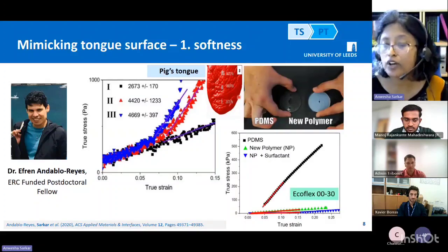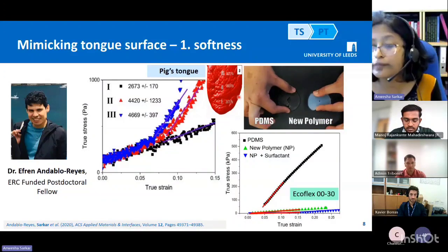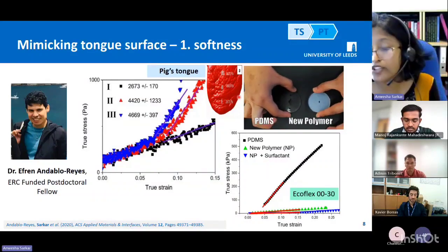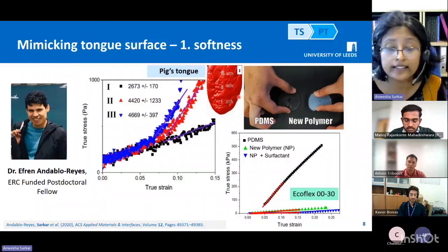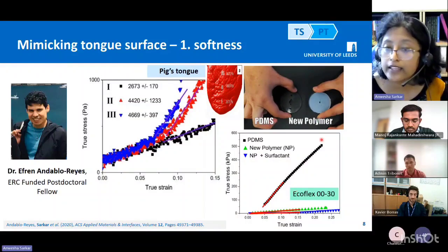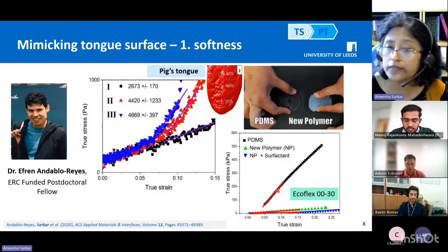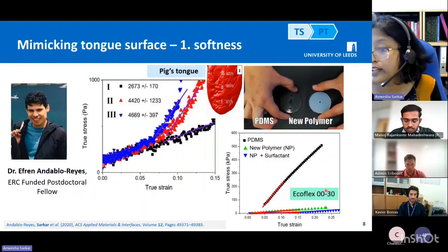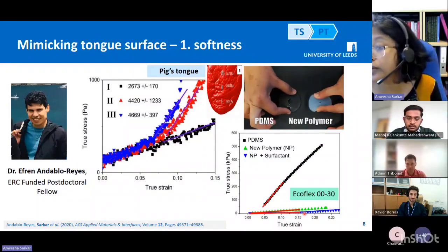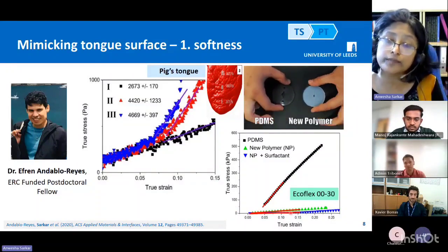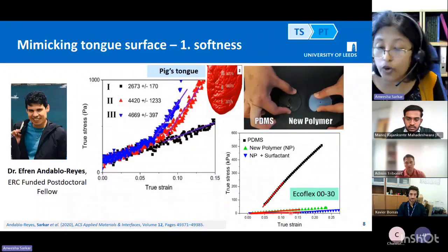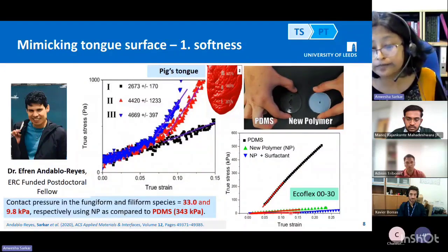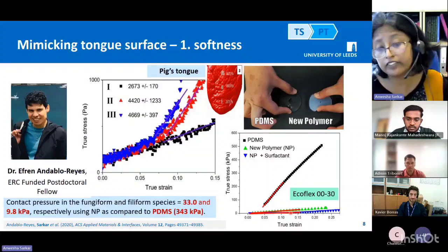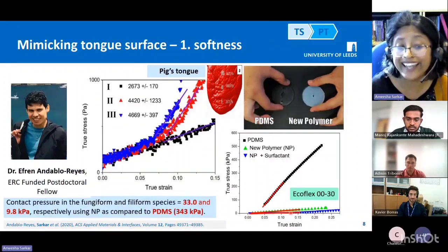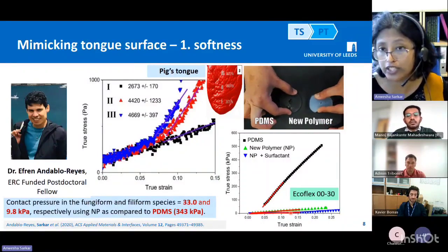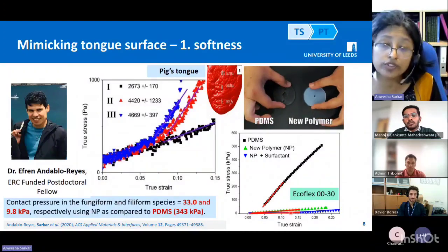So we said, okay, let's work on a new polymer, not PDMS, which is softer. And this was the new polymer which we worked on, which is EcoFlex, and some surfactant is added, and I will tell you why later. So what you can see here, this is your PDMS, which is a classic material. You're talking here about 500s of kilopascal, whereas in EcoFlex, you are getting much lower, because you're using a much, much softer polymer in terms of your true stress. So this is the first bit of the puzzle, which is the softness. What does it mean in tongue scale? You have converted the contact pressure of particularly the filiform and fungiform papillae to 33 and 9.8 kilopascal as compared to 343 kilopascal. So you're talking an order of magnitude lower, which is closer to a real human tongue.